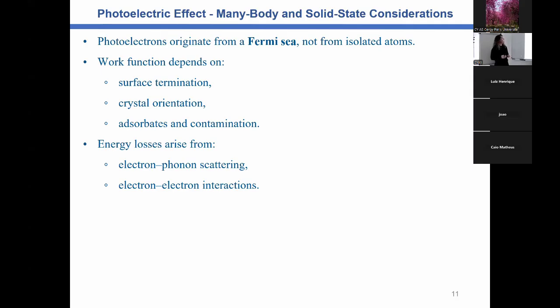So this work function will depend on crystal orientation. If we have some orientation with some doping, for example, there is a difference. And if we have a surface termination, for example, different energy or different morphology for some interaction with the surroundings.